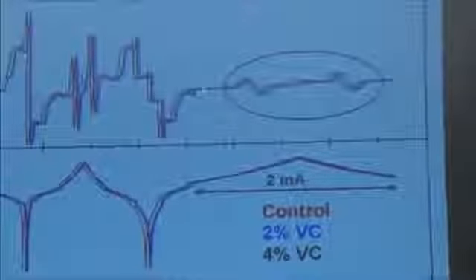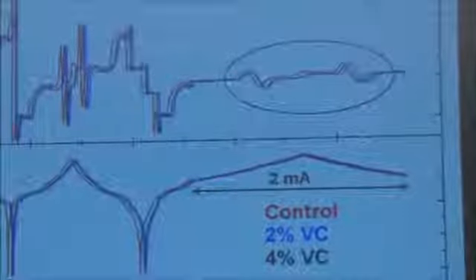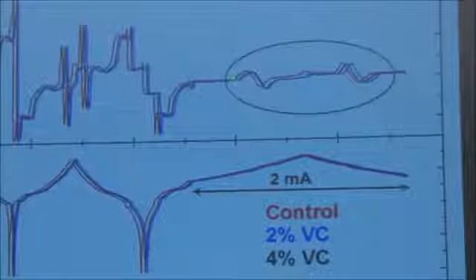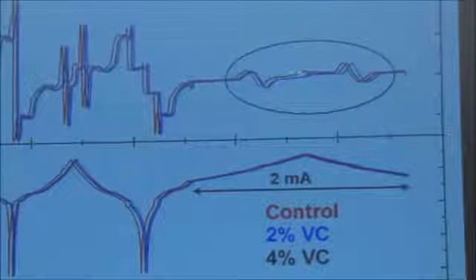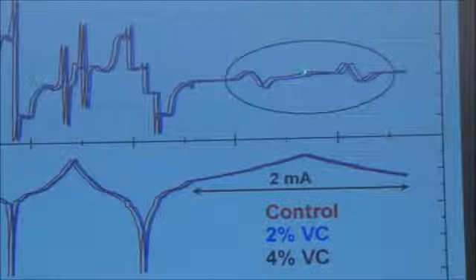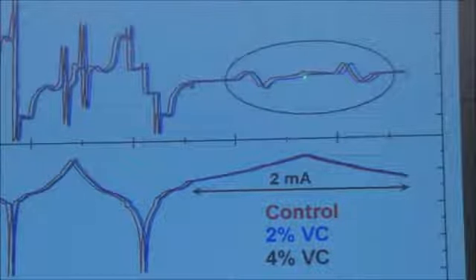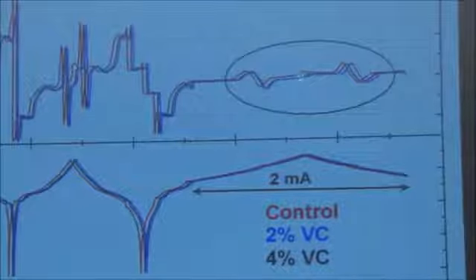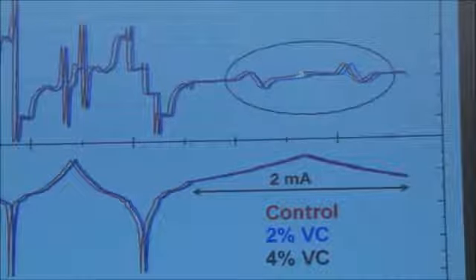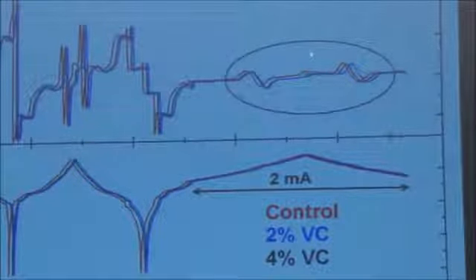So the entropy changes should be the same in all of them. The internal resistances are basically the same. So the only difference between the heat output in these cells is due to the parasitic reactions. And the heat from the blue and black is less than the red. Okay, so this is a crappy graph, right? It's what you would put on your screen just to see what happened.